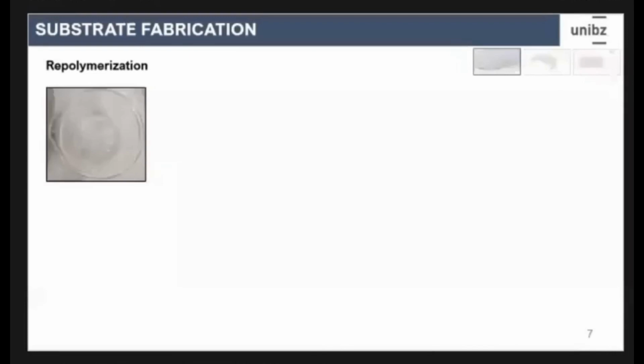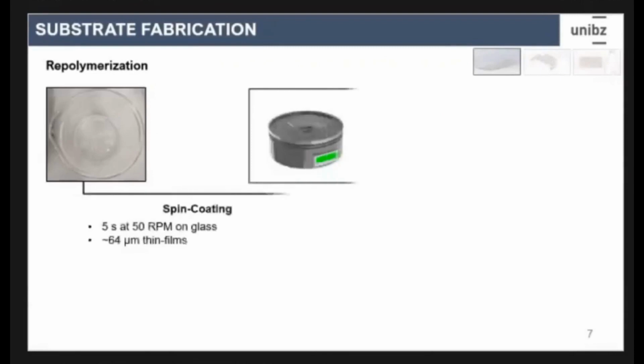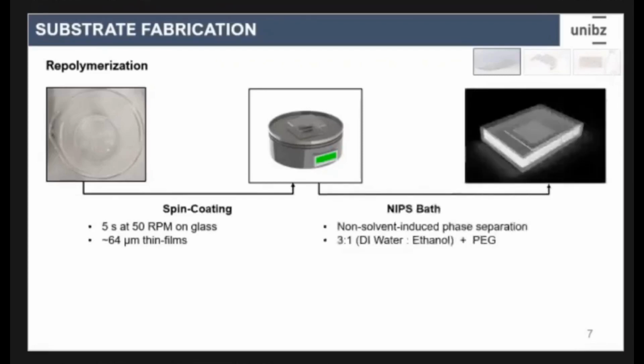So for the repolymerization, we take the viscous liquid that we created, which contains the plastic. Then, for the specific purpose of improving electronics and the temperature sensor, we spin coat it for 5 seconds at 50 revolutions per minute, and it yielded a film that was on average 64 micrometers thick. After spin coating, we submerge it into a non-solvent induced phase separation bath that consists of DI water, ethanol, and polyethylene glycol to bring the plastic back, or solidify everything at once, like freezing it.